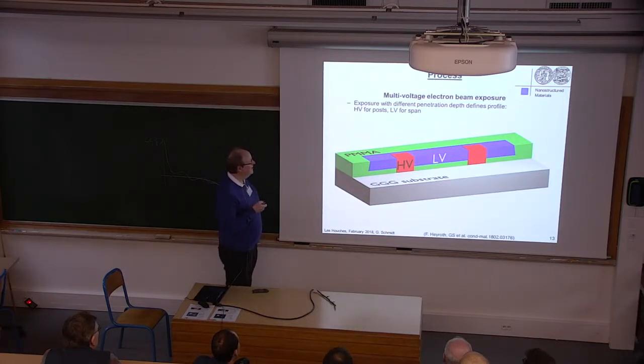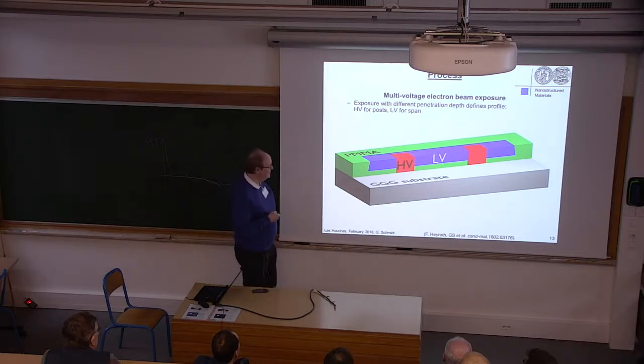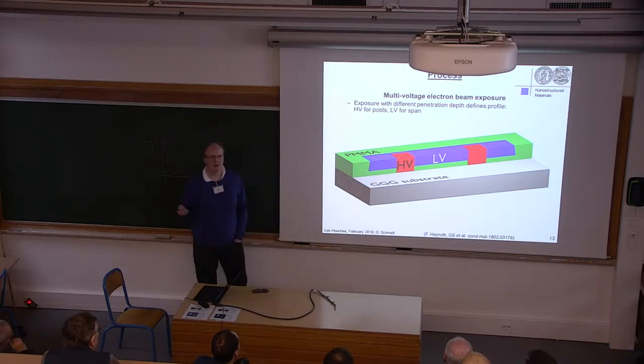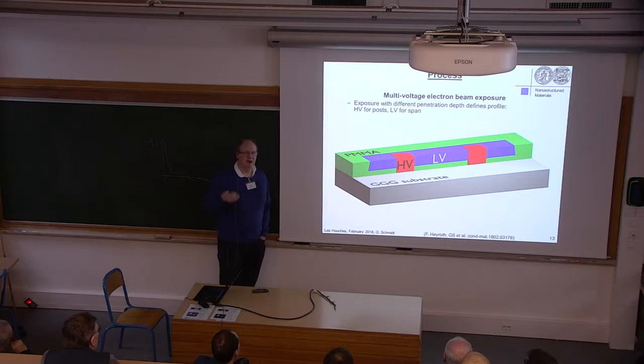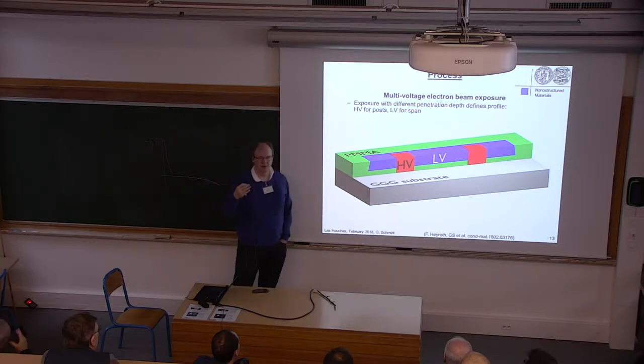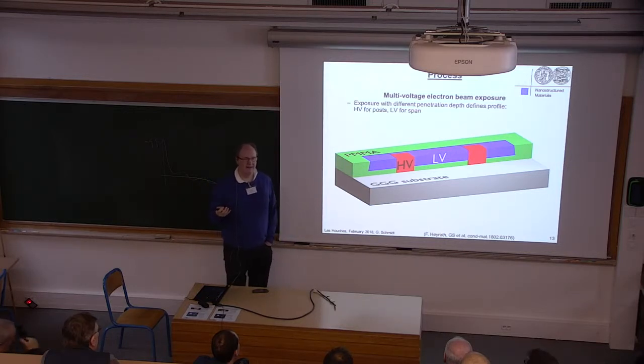I just want to emphasize a few things. So we're using standard PMMA. We just take a thick layer, and then we use low voltage exposure to expose the span of the bridge. Sometimes we also produce some kind of overhang. Then in principle you already have a cantilever. And if you use very low voltages, like for example 2.5 kV, then you only have a penetration depth of 170 nanometer. And that's a very strict limit.